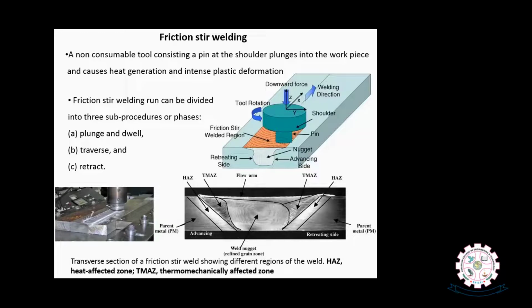In friction stir welding, when the rotating tool is inserted into the joint, the process is completed in 3 different steps. First, plunge and dwelling, and then traveling in a traverse direction, and then retract. You can see here the schematic diagram as well as the typical photograph obtained during the friction stir welding of non-ferrous metals. At the cross section, you can see the nugget zone. Usually in fusion welding processes, we will see a weld zone where cast microstructure appears because of the solidification of the molten pool in the weld zone.